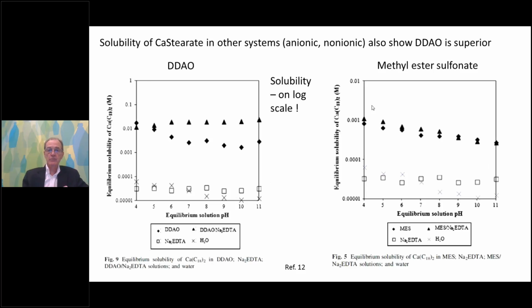There have been other literature references, again, on the equilibrium solubility of calcium stearate, comparing with other surfactants as well. In this particular reference, be careful, the solubility is now on a log scale, so there's a very big difference between the amine oxide on the left and the MES methyl ester sulfonate on the right. And again, what we see is the anionic surfactant, the methyl ester sulfonate, even with the presence of the chelant, is not as good at solubilizing calcium stearate as the amine oxide system by comparison.